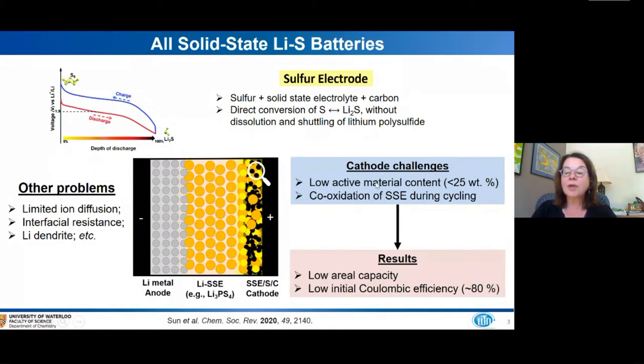Those include low active material content, often reported at less than 25 weight percent sulfur, 20 to 25, and of course the real problem of co-oxidation of the solid-state electrolyte during cycling. This is because the carbon is intimately interwoven with the solid-state electrolyte, and that wets the solid-state electrolyte thiophosphate, which is typically used in these cells, and thus causes oxidation. That in turn results in very low initial coulombic efficiency, often on the order of 80%.